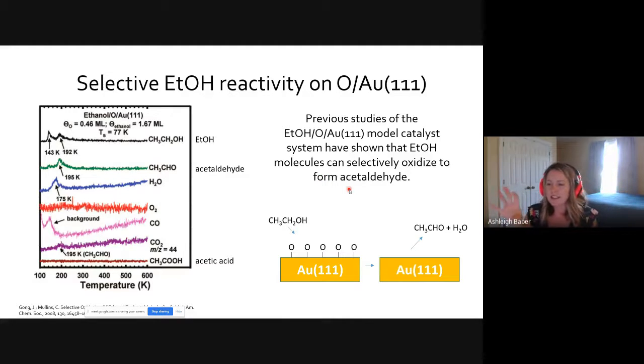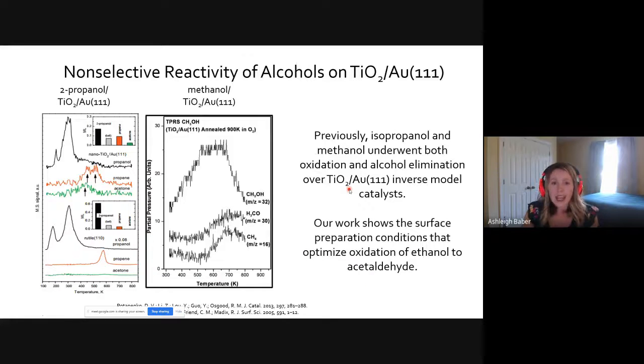Okay, so you get this full selective oxidation to form acetaldehyde, but then the oxygen runs out. And so our idea was, if we use titania, then we have a source of oxygen on the surface that's pretty easy to regenerate. We just have to anneal the titania nanoparticles, the whole system, in oxygen at high temperatures to regenerate that. And titania nanoparticles supported on gold, similar systems, have been used to study both 2-propanol and methanol, and similar stories were found with both of them.